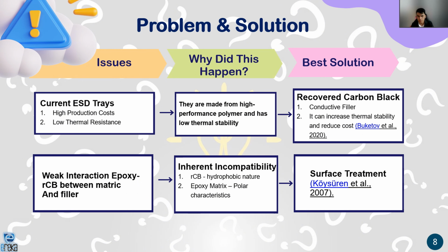So that's why we want to use the recovered carbon black, because it can act as a conductive filler. Based on previous research, it can help increase the thermal stability and also has a low cost. However, when we use the recovered carbon black, it can have lower interaction between the matrix and the filler, which can cause lower properties of our products. So we want to apply surface treatments to achieve better compatibility between the matrix and the filler.